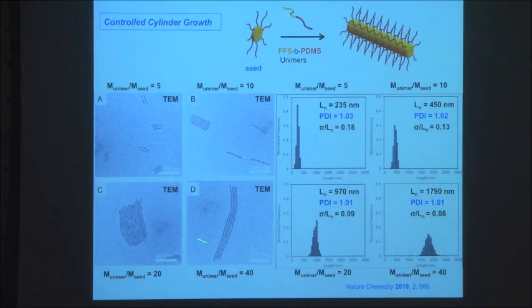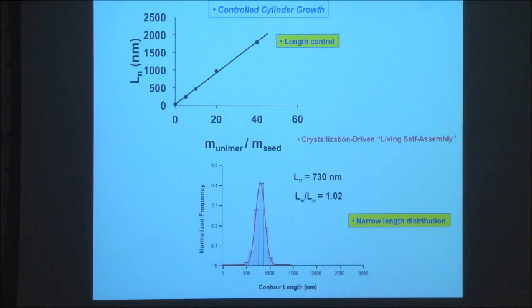And so you can generate structures that all have the same length, and you can control the length. And here's the length distribution. You can create a polydispersity index in length here, and you see values all very close to 1. And you have control from 100 nanometers or so up to several microns in this process. If you plot the length against the ratio of the unimer to seed, you get a straight line, so you have length control. If you want cylinders of length 700, you can choose this ratio. You generate cylinders of length 700.